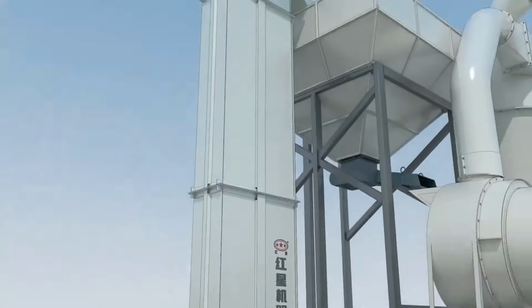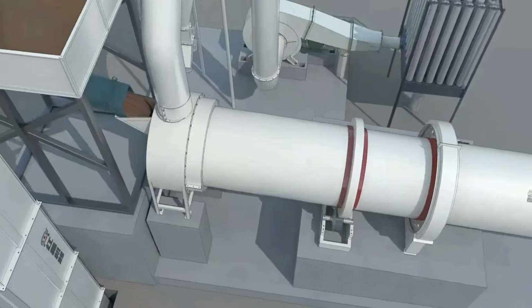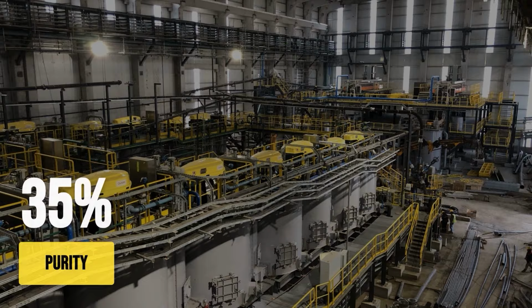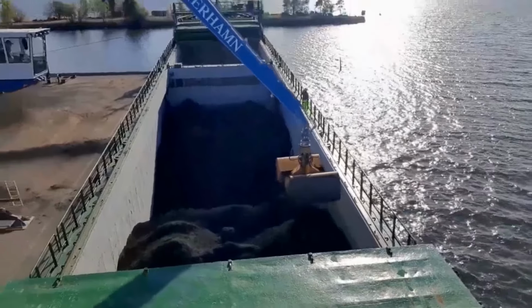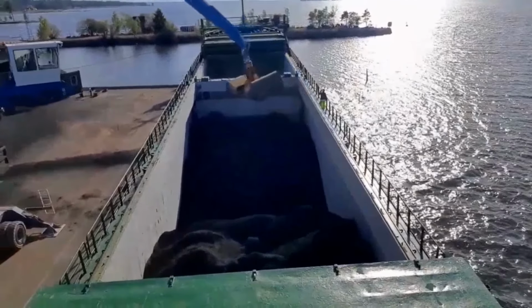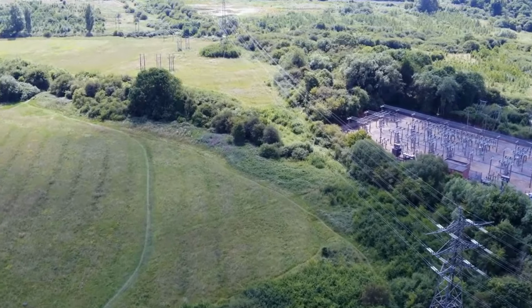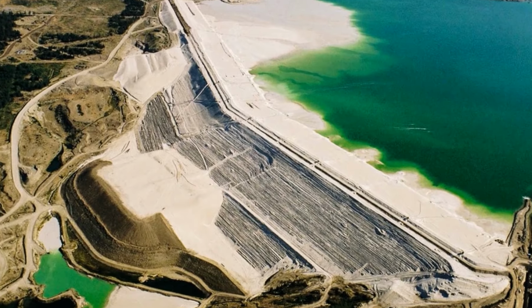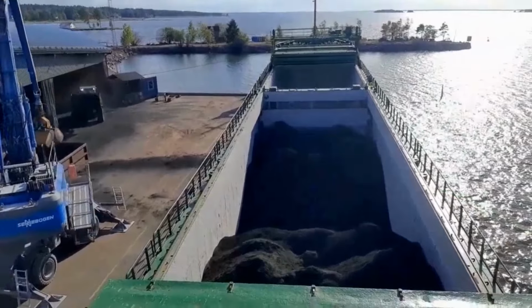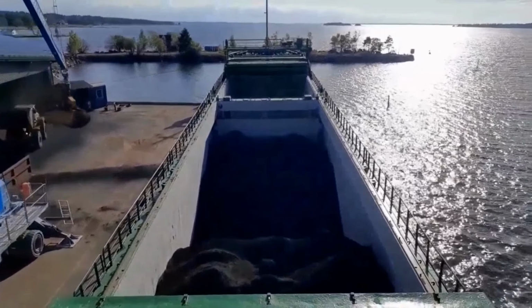This froth is skimmed off, then dried, forming a dense copper concentrate. At this stage, purity jumps from barely a fraction of a percent to as much as 35%. Each ton of concentrate carries the promise of a metal that will soon carry power through millions of lives. The leftover slurry, called tailings, is pumped to secure dams, where it settles safely out of the production line. What remains is a feedstock ready for fire, the next step in copper's transformation from stone to metal.